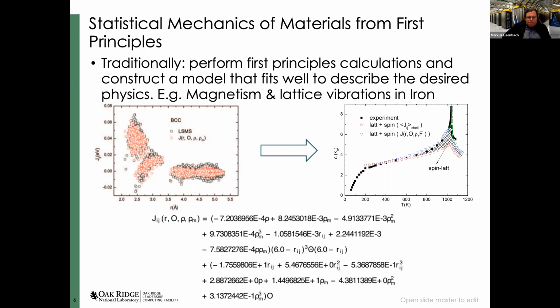So it mainly comes from the fact that by this coupling, you increase the amount of fluctuations in the system. Because you can have momentum and angular momentum transfer between the different subsystems more easily. So you increase the overall fluctuations, which is basically a measure for the size of the specific heat. If you do not have the coupling, you have basically separate subsystems that are not talking to each other as effectively. I see. Very, very nice. I did not know about this. It's very impressive. Thank you.